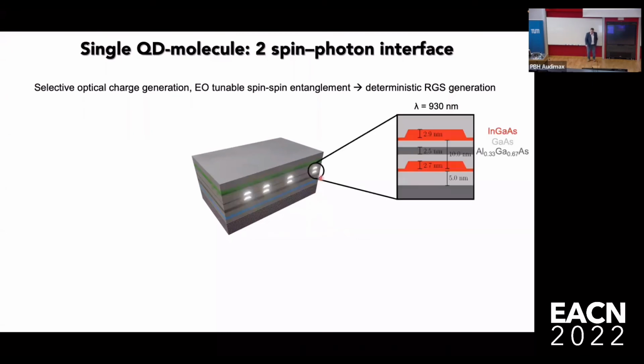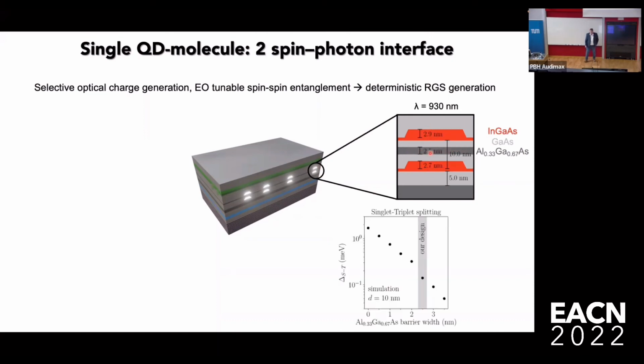So there's the molecules grown, in this case in Bochum. They have exactly these dimensions. So the heights are accurate to within 0.1 nanometer. They're separated by about 10 nanometers, and they have a tunnel barrier to suppress the strength of the tunnel coupling between the 2 quantum dots forming the molecule. There's the strength of this singlet triplet splitting that I just showed you. So we're aiming for something which is around about 0.1 milli-electron volts, 100 micro eV or so.